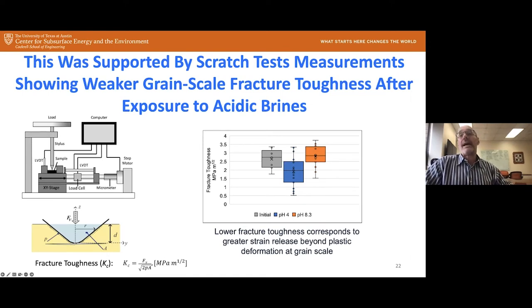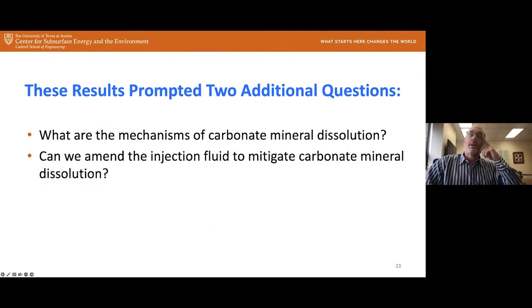And what you find is that the fracture toughness after the experiments at lower pH is less than at the reservoir simulated pH and less than the original sample. So this shows that we are indeed compromising the geomechanical integrity of the rock, and that we're increasing the porosity and decreasing the amount of dolomite with the acidic brine, and that's allowing this fracture or this strain release to occur. So these results prompted two additional questions.